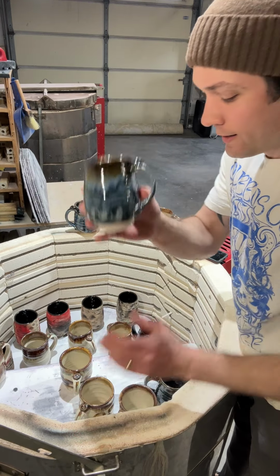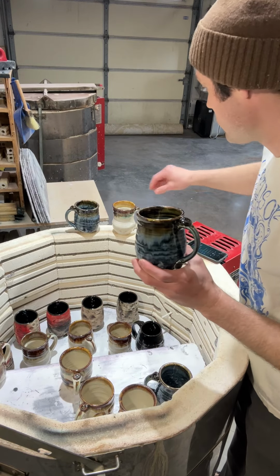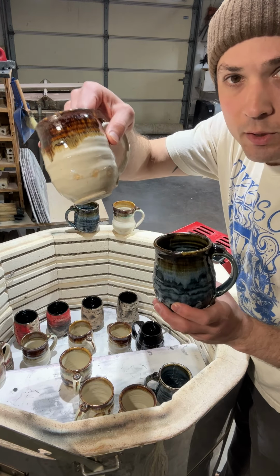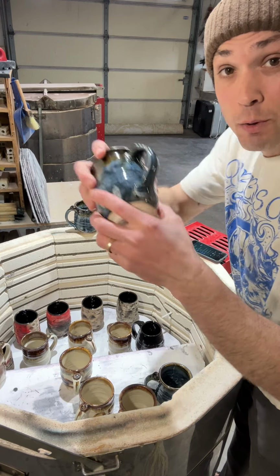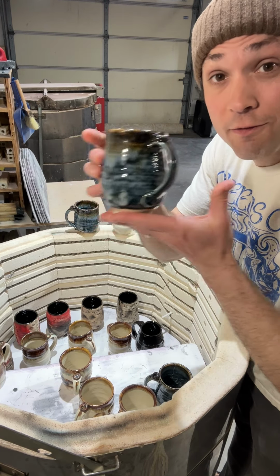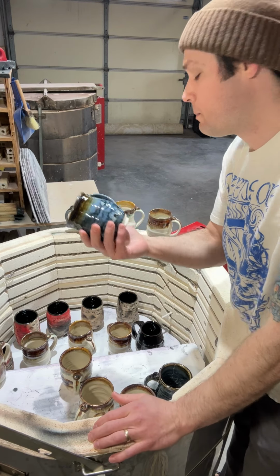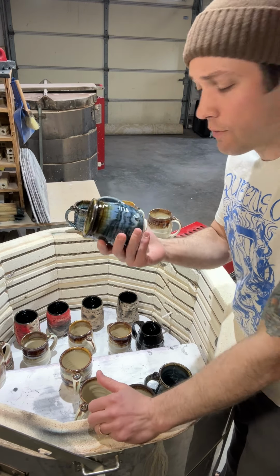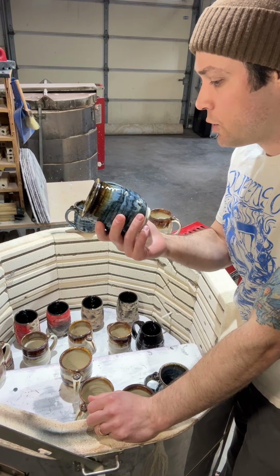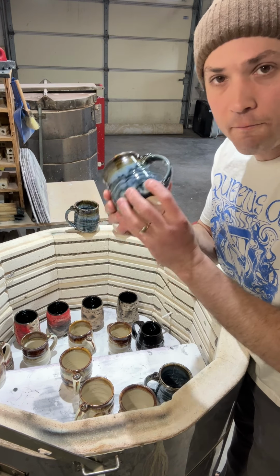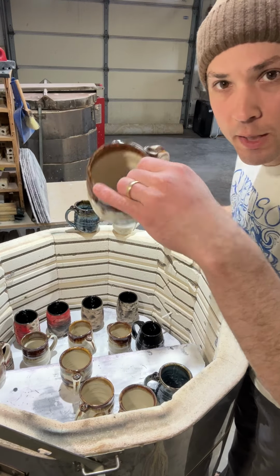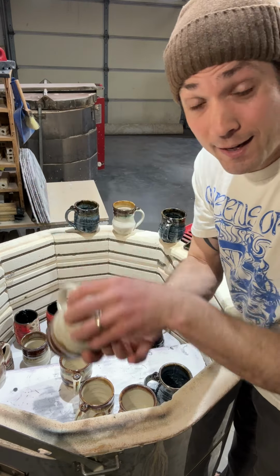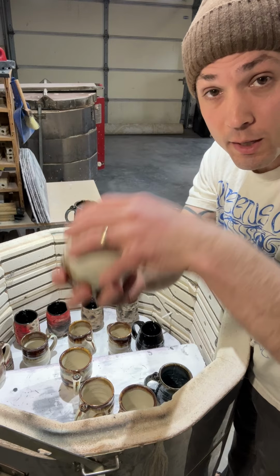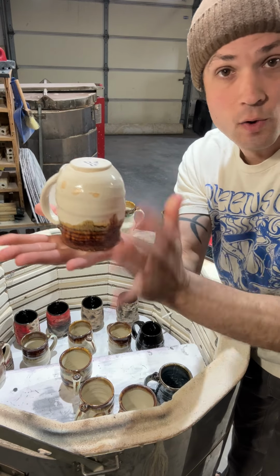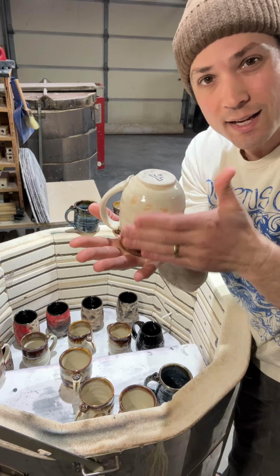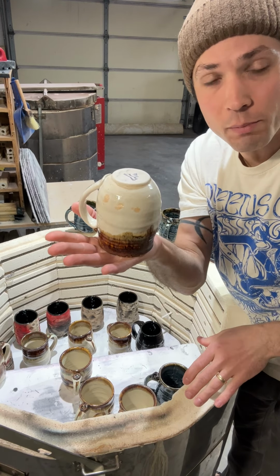So this is interesting. This pot is essentially the same process as this, where I brushed iron, dipped in Nuka, but what happened was I forgot to put my signature on, so I needed to refire these again. Well, in refiring them, sometimes I'll get this bubbling texture that's not very nice. So what I do to prevent that, I take the finished pot, just like it is now, and dip it in a black glaze, and then I set it upside down and let it dry out in the sun, because it's not absorbent, but the glaze will stick to the outside a little bit. It's like a thin coating of a black glaze.